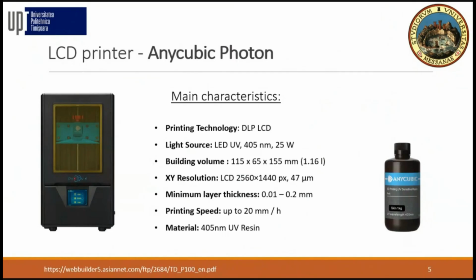So we use a commercial 3D printer. The technology is DLP, digital light processing, using as a light source an LED with 405 nanometers wavelength and power of 25 watts. The building volume is not so big. It's around 100 millimeters or less. This is the reason that we were somehow constrained on the dimensions of our specimens. It has a very good resolution, 47 microns. The layer thickness is between 0.01 to 0.2 millimeters. The printing speed is up to 20 millimeters per hour, and the resin is a commercial resin for this printer.